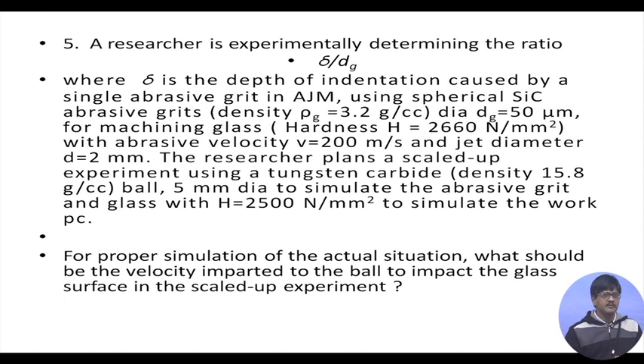But he is not doing the experiment with this one. He is doing the experiment with a scaled up model where he is using a tungsten carbide ball with a density of 15.8 grams per cc, and the diameter of the ball is 5 millimeters. So, instead of 50 microns, which can hardly be seen by the naked eye, he is using 5 millimeter diameter.